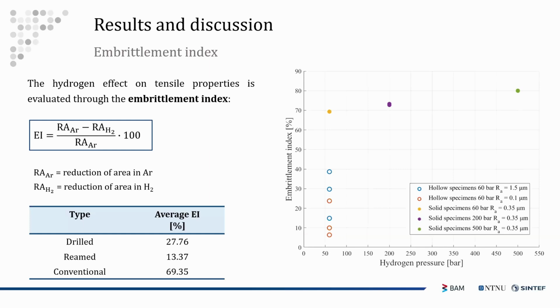So the higher the embrittlement index, the higher will be the impact of hydrogen on the tensile properties of the steel. In the graph on the right-hand side, you can see that the tests were conducted with all the specimens, either drilled and reamed at 60 bars, and also at 60 bars with the solid specimen, but we have conducted other tests with solid specimen at higher pressures, up to 500 bars, in order to exploit as much as possible the capability of the autoclave.